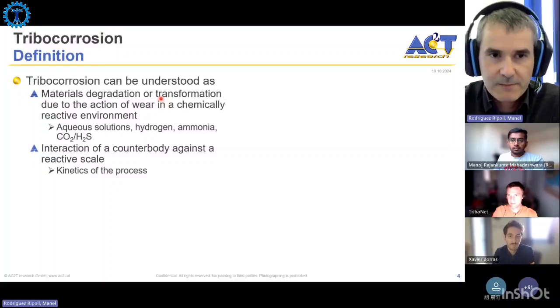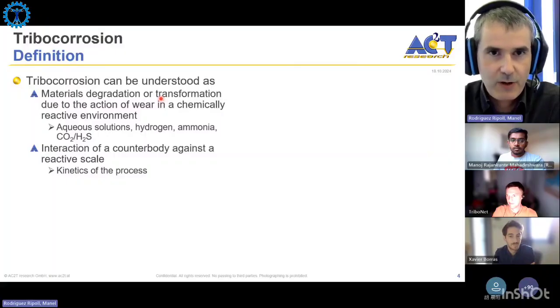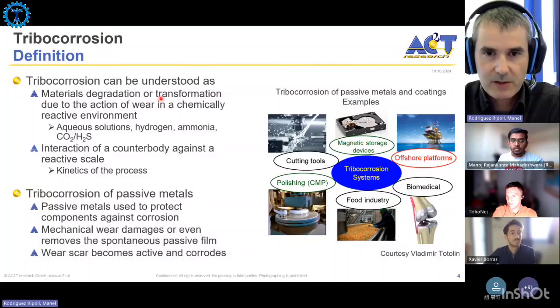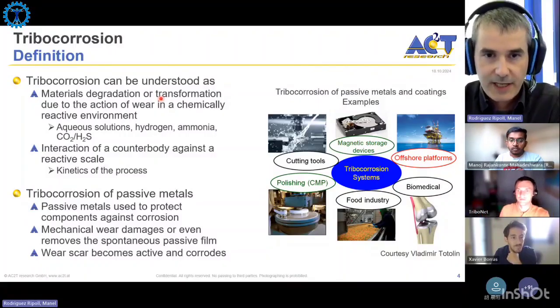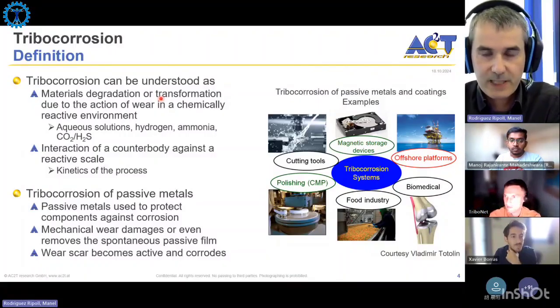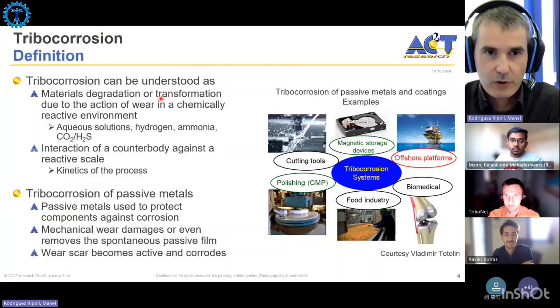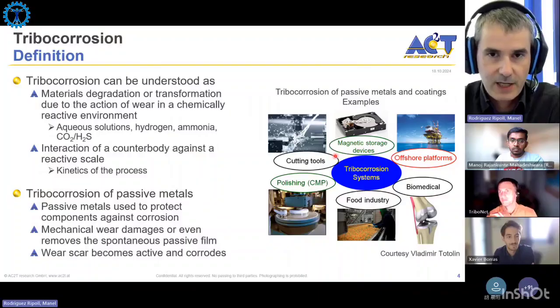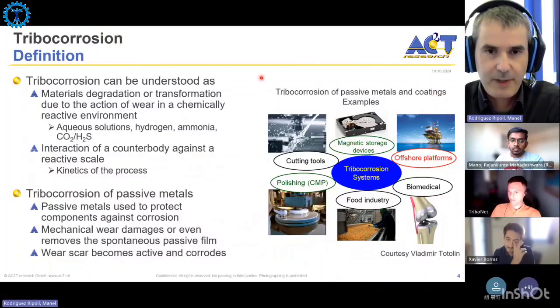So this plays a bit, but basically what we will focus on today is the synergy, and this synergy is most visible in passive metals, because passive metals are metals that are corrosion resistant. So these metals are used to protect components against corrosion, and they rely on the spontaneous formation of a passive layer. And when we mechanically destroy this passive layer, then we have the paradox that a metal that should be corrosion resistant starts corroding. And that's the place where tribocorrosion is most obvious, and this is the place where tribocorrosion has been most intensively researched in the past years.